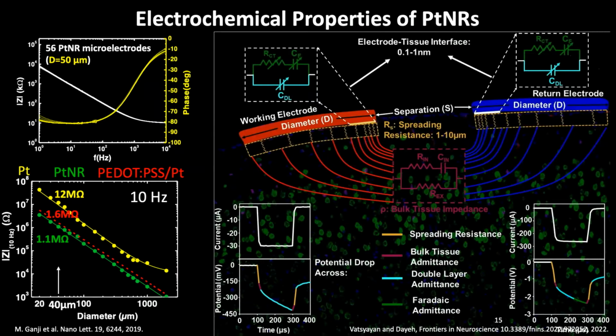For stimulation, you would want to inject sufficient charge density to stimulate the tissue without leading to adverse effects, without damaging the tissue. And to understand that, we used a parametric characterization of the electrode tissue interface. Here we're looking at what may look like a complex picture, but it's really not. This is for bipolar stimulation between two contacts. And the interface is modeled as a simple Randles cell that has a double layer capacitance for capacitive interaction, a Faradaic or redox branch.